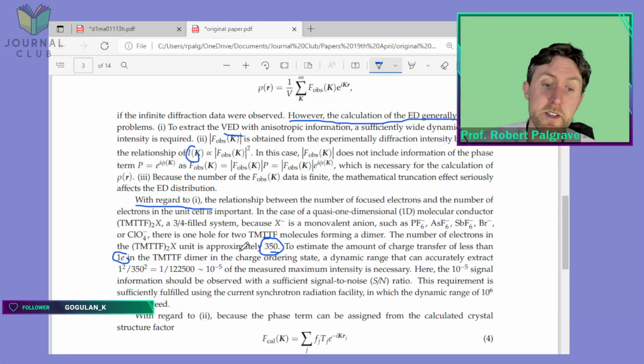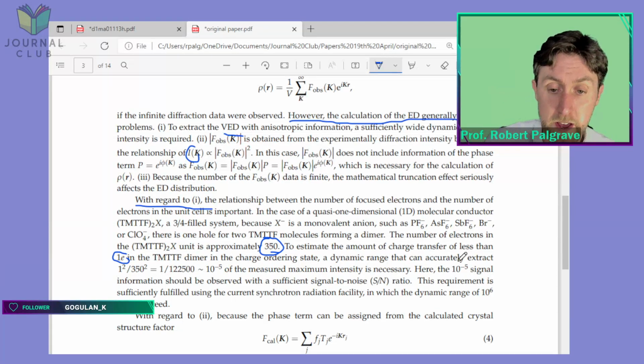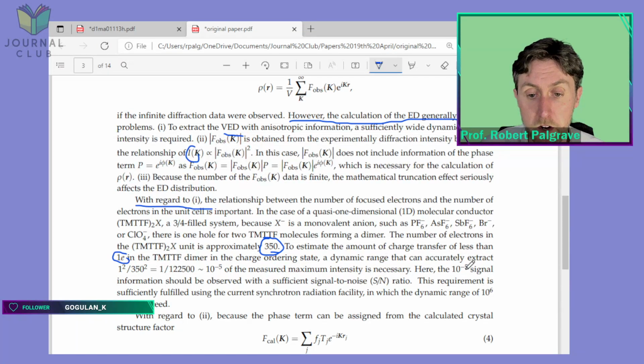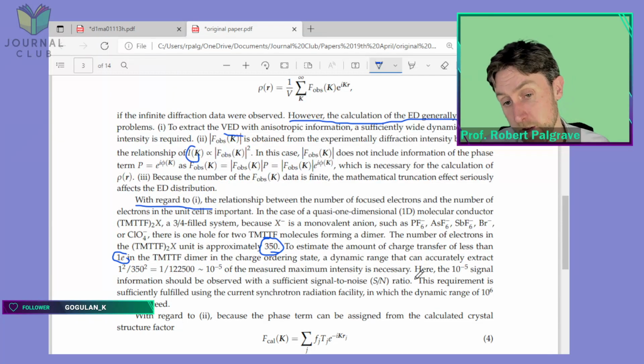So you need to be able to see changes of 10 to the minus 5 compared to the maximum intensity. So 1 part in 100,000. You need to be able to see that difference in your signal. That's technologically challenging, but this is what they can do at the synchrotron. This is why they do this experiment at SPring-8, because the 10 to minus 5 signal information should be observed with a sufficient signal to noise ratio. Okay, so there we go.